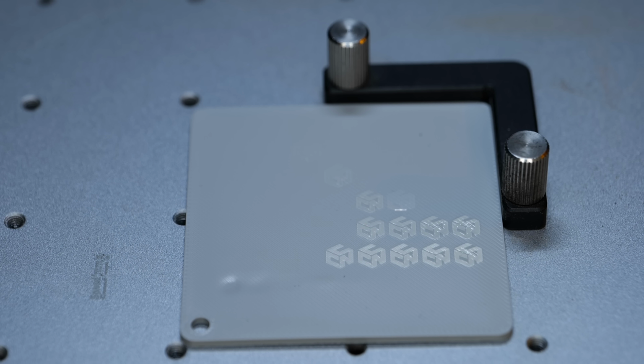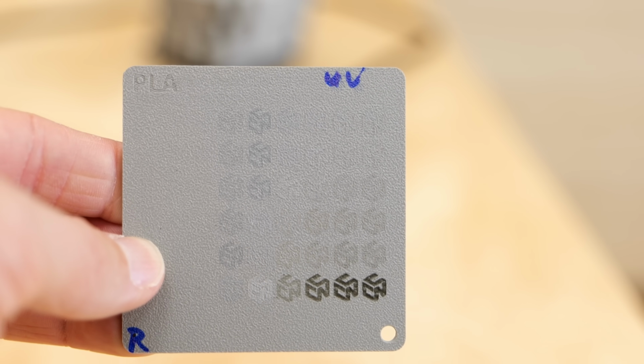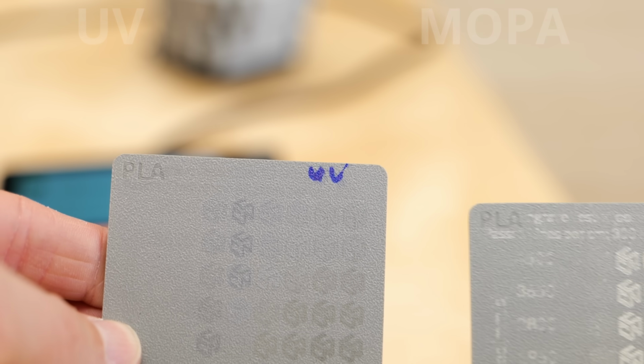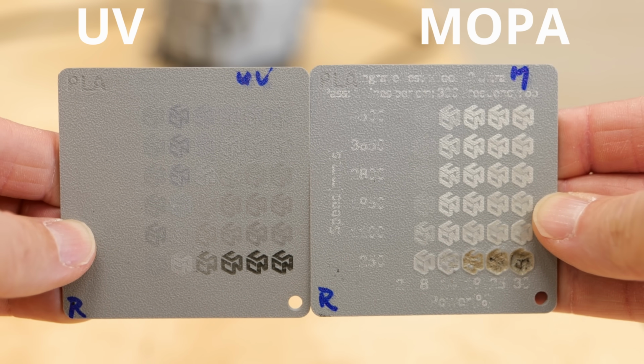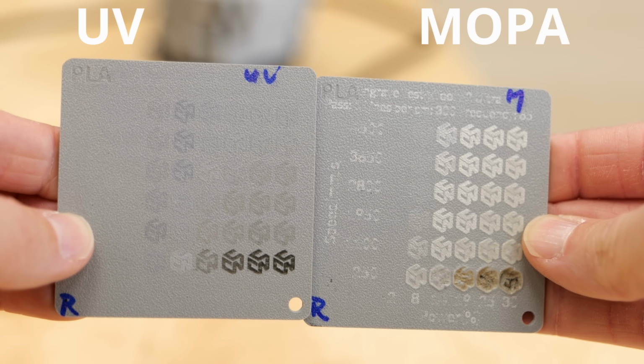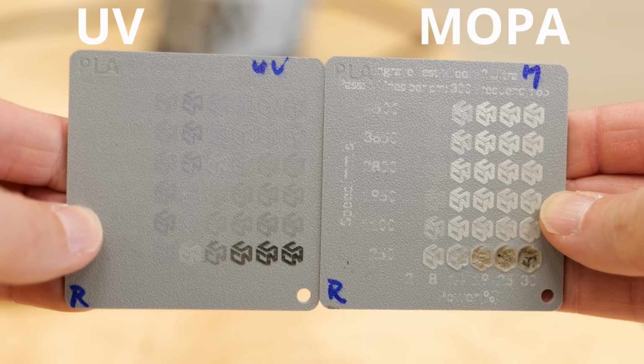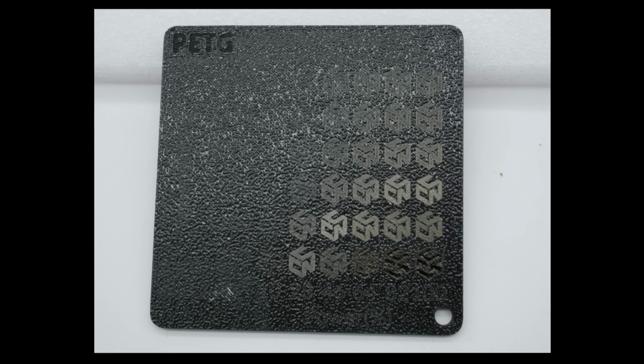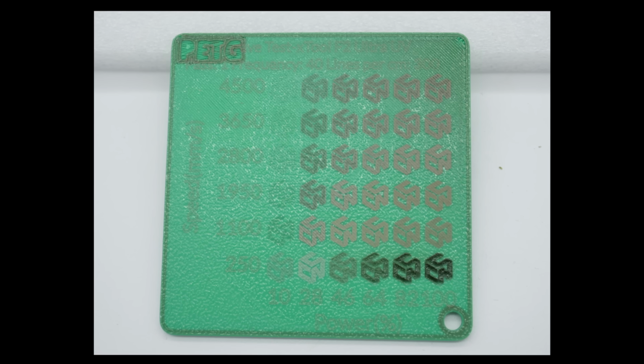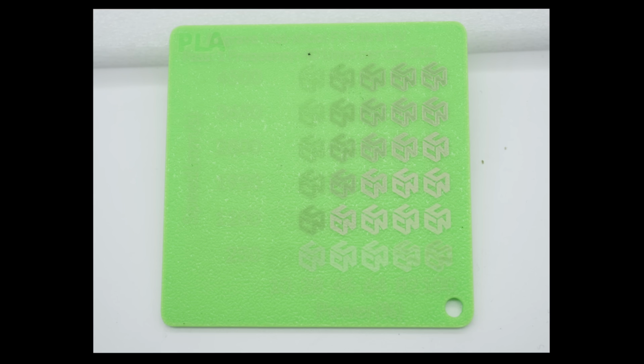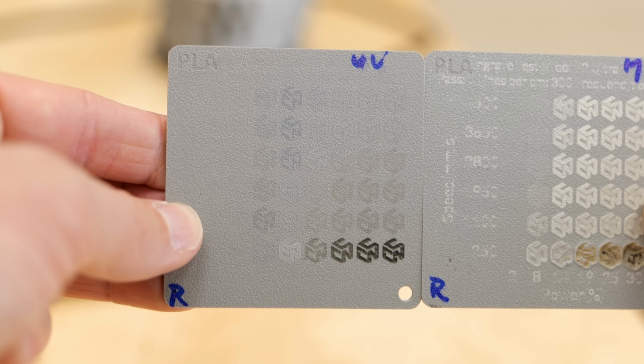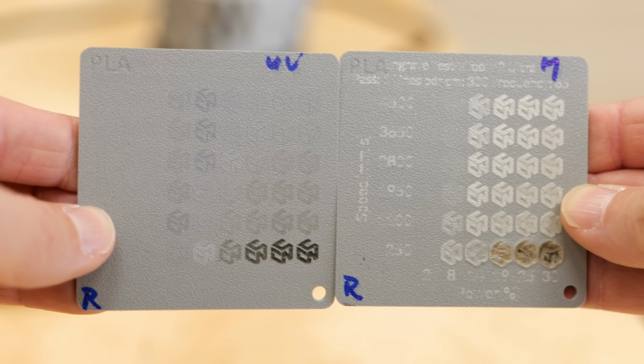And of course, because this is how testing always works, that exact color gave me one of the worst contrasts of all of the samples, especially with the UV laser. The MOPA laser actually performed a bit better here, which was uncommon compared to most of the other materials. Looking closely at the other samples, many UV laser markings had a slightly gray hue, which is more or less the base color of the filament. So there simply wasn't much contrast to create.